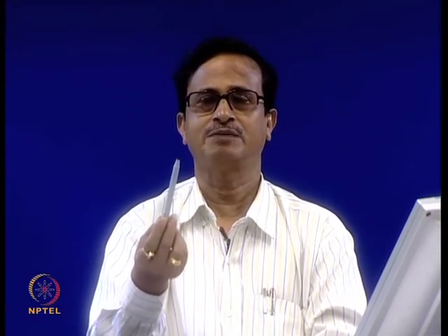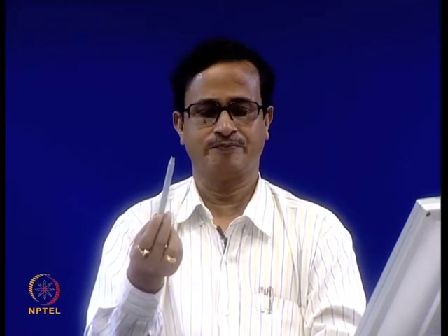Say PVC, I told you you can have rigid PVC as well as flexible PVC. Rigid PVC you have seen, say in medicine foils, where capsules or tablets are packed with the help of some transparent plastic sheet. Those are rigid PVC sheets, whereas the same PVC when it is mixed with some ester plasticizer like dibutyl phthalate becomes flexible, leather-like. So, plasticized PVC is known as artificial leather, whereas rigid PVC does not contain any plasticizer.